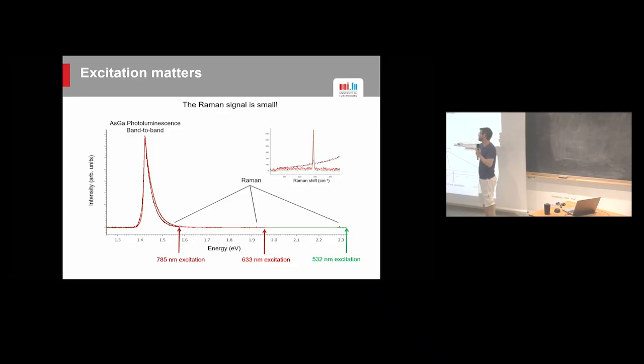But I mean, look at the competition they have here, right? So if your sample has this sort of photoluminescence, of course, you want to move away from it. And if you're too close, as you can see here, well, the colors are not great. I hope you can see, but for the infrared excitation, your Raman peak falls already in the foot of the photoluminescence, and it gets really weak and not great. Okay, so this is one of the practical reasons why wavelength matters.